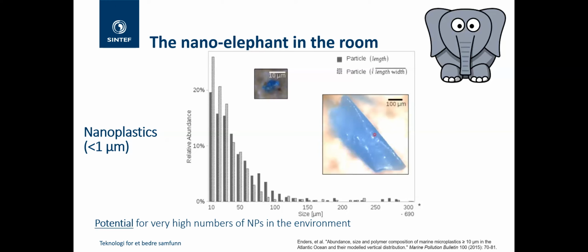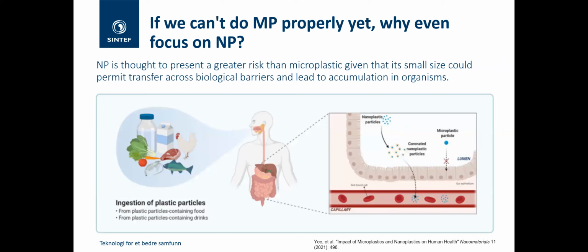So we're increasingly seeing from the exposure assessment studies, when people have gone out into the environment and taken their water, sediment and biota samples, that typically as you go down in size, the relative abundance of particles increases almost exponentially as you go from 1 millimeter down to 10 micron. From this, we would infer that as you go below 10 micron in size and into the nanoscale, this exponential increase would continue. The reality is there's potential for very high numbers of nanoplastics in the environment, but we lack the extraction techniques, the sample processing methodologies, and the analysis techniques to be able to look at the nanofraction properly. There's been a few studies, as we'll see in a second.